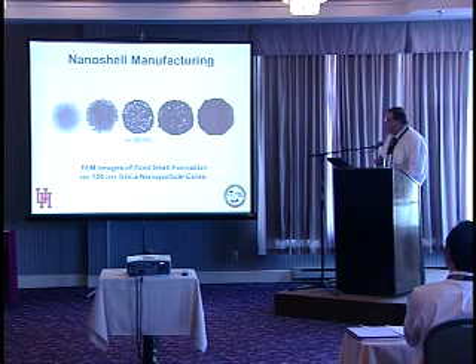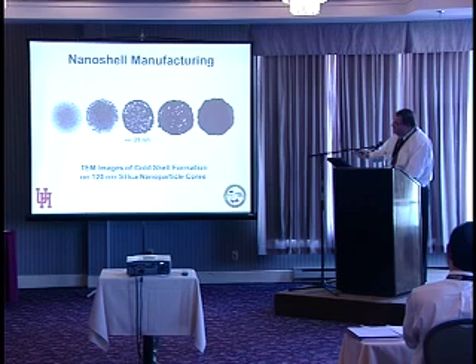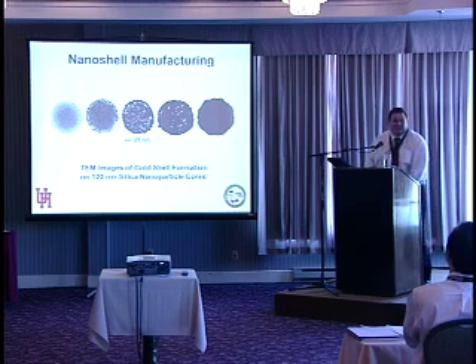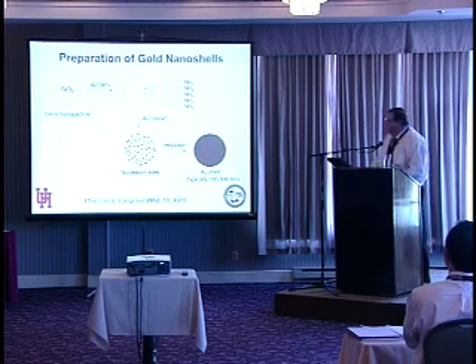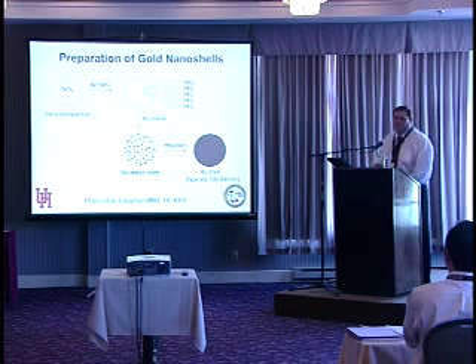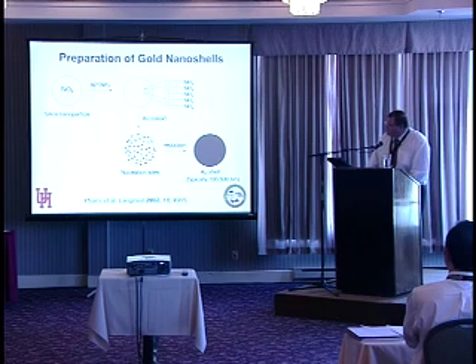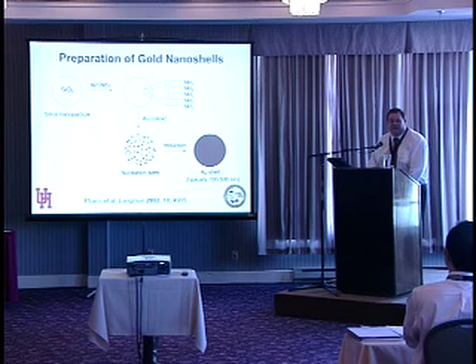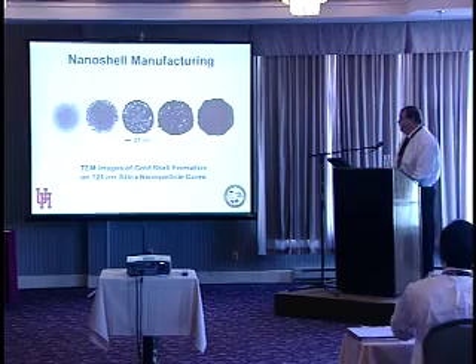Here is this process demonstrated schematically. Here are the seeds on the particle. We start the reduction process, the shell grows, and then finally we have a complete shell. Now, as shown here, it looks quite simple. It's an involved process. It turns out that even my best students with considerable experience in making these shells can reproducibly make these particles about 1 out of 3 times. It's a very complicated process. It's not easy to do.